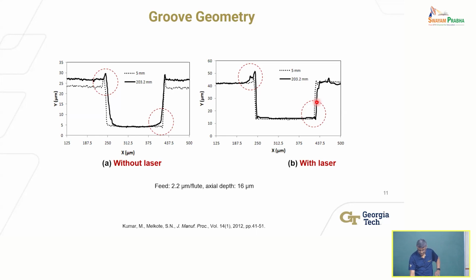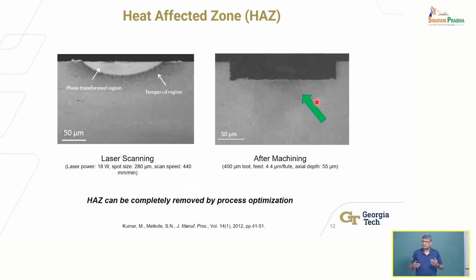So in the end, but initially, this is what we found. What happens to the material below it? As I said, we want to only irradiate the volume of material, soften only the volume of material that the tool is going to remove. Anything more than that is probably bad, because you're starting with a very hard material, and that's because you want the final product to have high strength, right? Therefore, you want to make sure that after you remove the material, you have not lowered the strength of the material, right? Which would happen if I don't control my energy source or the laser matter interaction properly, okay? Or the amount of energy I'm inputting into the process.